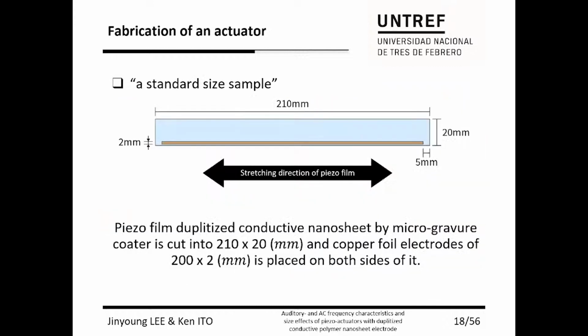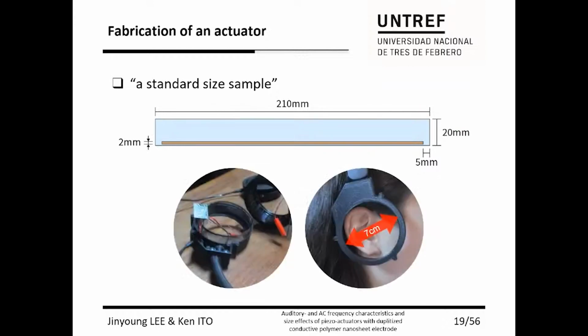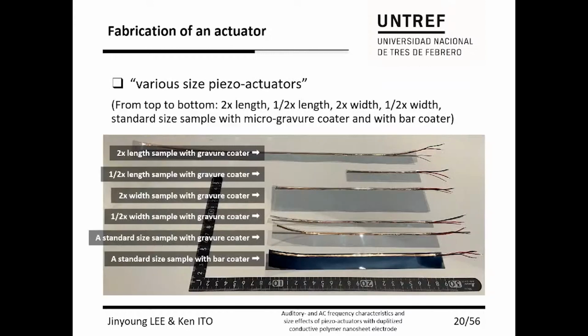We cut the film printed with nanosheets into these sizes. The longer side is the stretched direction of the piezoelectric film. We fixed this size as a standard sample based on the diameter of 7 cm, which doesn't touch the ear lobe when the actuator is curved. Based on the standard size, we fabricated samples changing size to twice and half the size. Also, a bulk sample laminated at micrometer order with a bar coater was prepared for comparison.